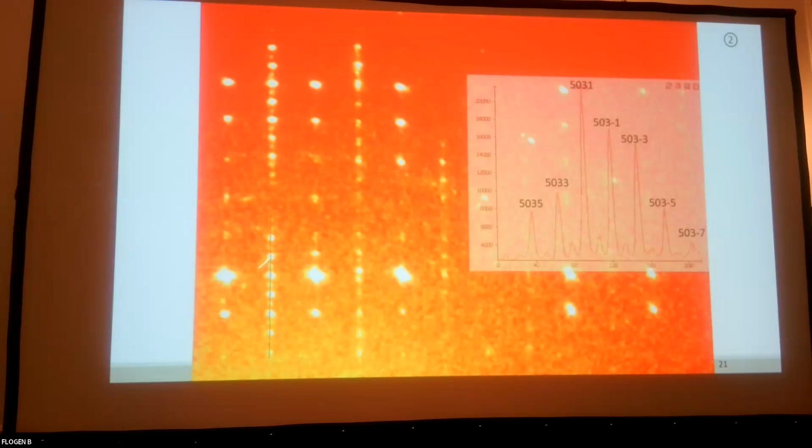And this is the case where the satellites are fairly well resolved, but if you're looking then at rows like this, there is not only one set of higher order satellites in between, but there are actually several sets of higher order satellites. And then the intensities are overlapping, and this is what is causing those relatively poor R values for the higher order satellites.